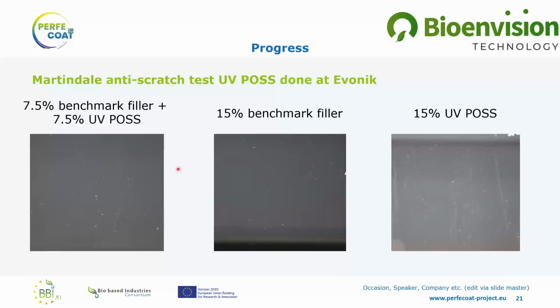Next, we try to see if there was any synergistic effect between the benchmark and the POSS. And here we have 7.5% of the benchmark filler plus 7.5% of UV POSS, while the other one is just 15% benchmark filler, and the last one is 15% UV POSS. And as you can see, an increased amount of POSS does not necessarily lead to better mechanical strength. And compared to the 15% benchmark filler, there isn't a greater synergistic effect between the POSS and the filler.